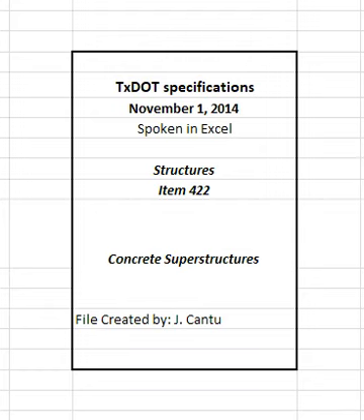4.8.1 Cotton mats. Keep the concrete continuously wet by maintaining wet cotton mats in direct contact with the concrete for the required curing time. Weight the mats adequately to provide continuous contact with all concrete. Cover surfaces that cannot be cured by direct contact with mats, forming an enclosure well anchored to the forms or ground so outside air cannot enter the enclosure. Provide sufficient moisture inside the enclosure to keep all surfaces of the concrete wet. Use of soaker hoses and plastic covering is acceptable provided the concrete surface remains continuously wet for the required curing duration.